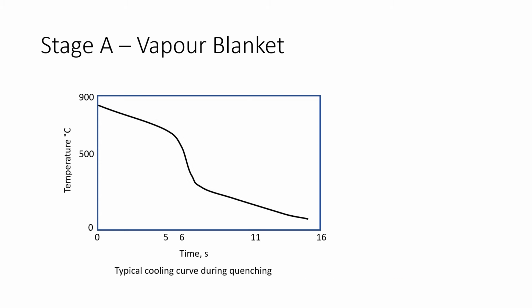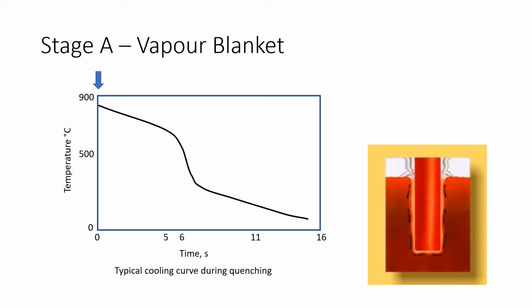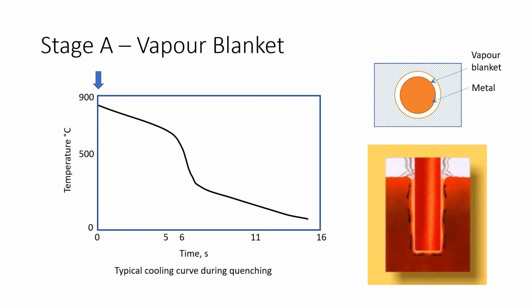This is a typical cooling curve during quenching. Immediately after the start of the quenching, the coolant or the quenching medium will get vaporized due to the metal being at high temperature, and a continuous vapor blanket will envelop the surface of the object. Now, no liquid can come in contact with the metal surface, and heat escapes from the hot surface very slowly at this stage by radiation and conduction through the layer of water vapor through the liquid vapor interface.